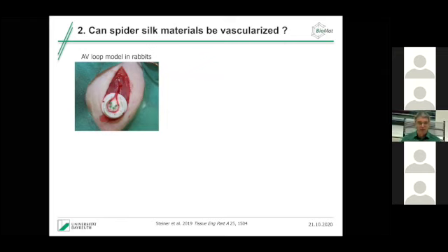And for that, we hooked up with a team from Erlangen, and they are specialists in a so-called AV loop model in rabbits. AV stands for arterial venous loop. So actually they cut open an artery and a vein, and then they artificially connect them, and they put it in such a Teflon pan. So you see here, the artery is coming in, and then it's going over into a vein, in a Teflon pan. And inside the Teflon pan, now you can place a lot of materials. And if they are actually good materials, the vascularization from this AV loop into the material will start.